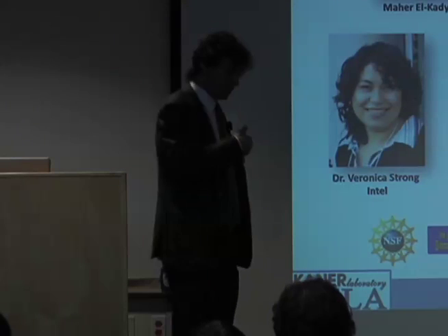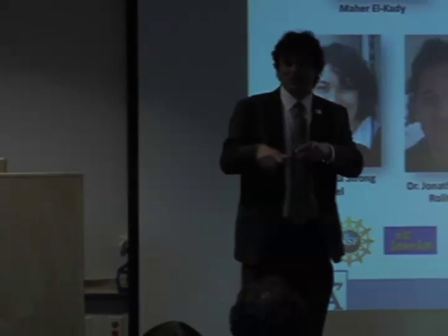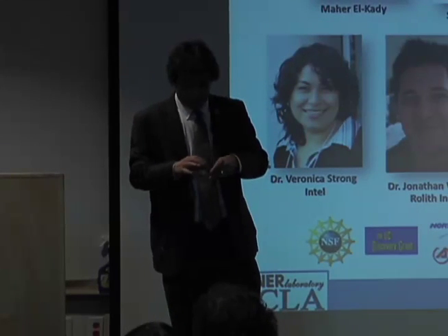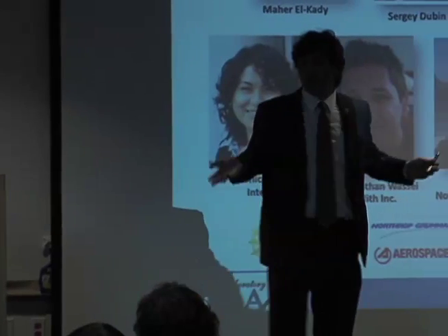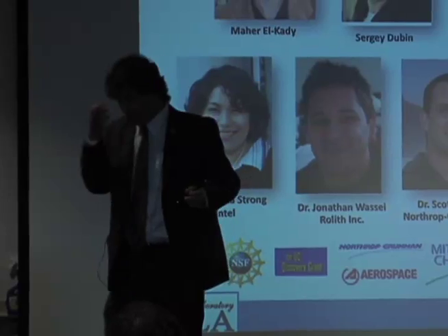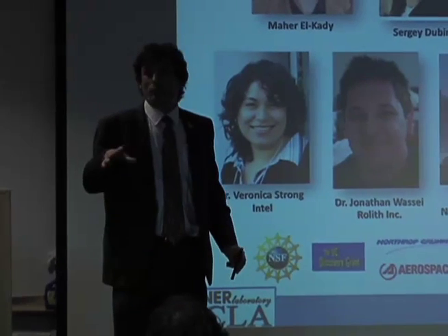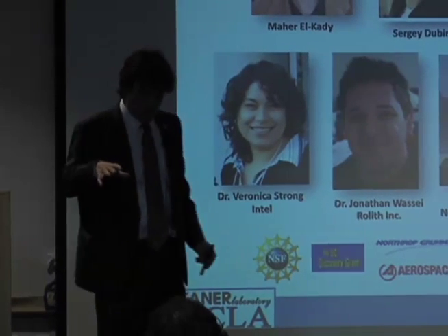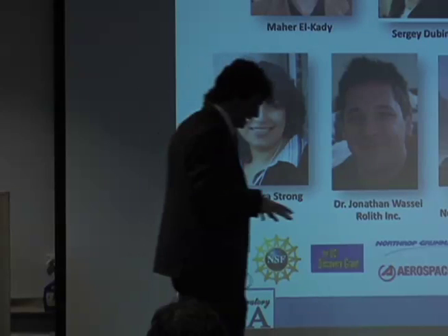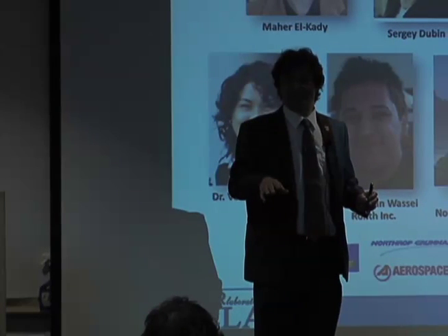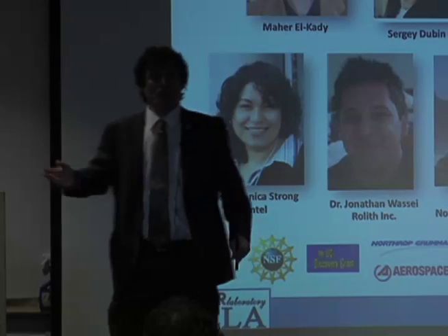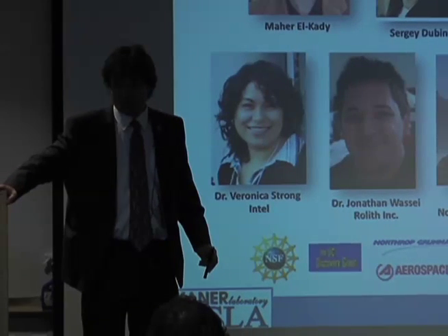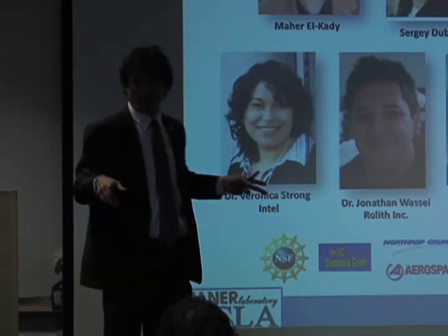So especially with our stuff where you already have carboxylic acids and hydroxyl groups, one of the things that I should tell you is if you hit this with a laser, you may ask, what's the carbon content at the end? Because the graphite oxide is 30 to 40% oxygen. When we're done at the end of the day, we do this in air, we routinely get 99% carbon, 1% oxygen. The best we've ever done in air is 99.7% carbon. So it's amazing how well these deoxygenate.